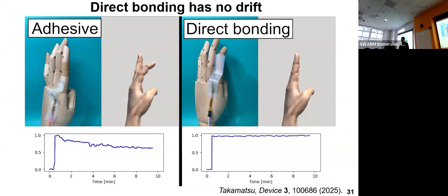Okay, both are very good questions. For the oxidation point, we tried to use oxygen plasma treatment to make the direct bonding, but we failed. So water vapor plasma is a very important technology. I'm not sure whether you can have access to water vapor, but oxidation should be avoided to make the bondings. Oh, but water vapor is oxidizing? Normally this causes re-oxidation, but the H gases could be generated inside the chamber. So this then makes de-oxidation instead of oxidation. Okay, even though there's still oxygen.